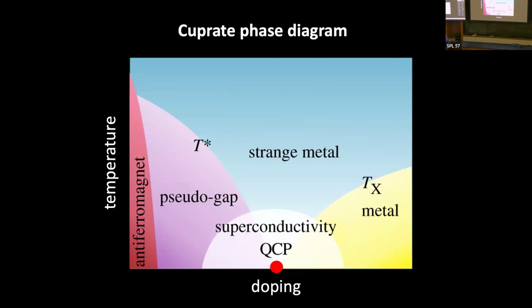So here's a cartoon phase diagram of what we have in the cuprates. We don't know what the phase diagram looks like in the Hubbard model, but hopefully it looks something like this. And these are just some of the key phases. There are many other rich phases that are skipped. So this is in temperature and doping. In the cuprates, the electrons are interacting quite strongly. So if you go to the regime of half filling, or in an undoped system, where you have an average of 1 particle per site, you crank up the interactions, then you find that what the system wants to make is something called the Mott insulator, where you form 1 electron per site, because you want to suppress density fluctuations that cost interaction energy. Now, if you lower the temperature further, you get an antiferromagnet.